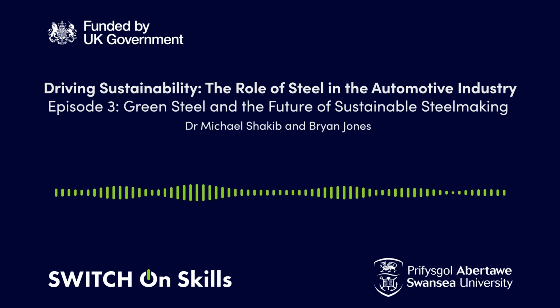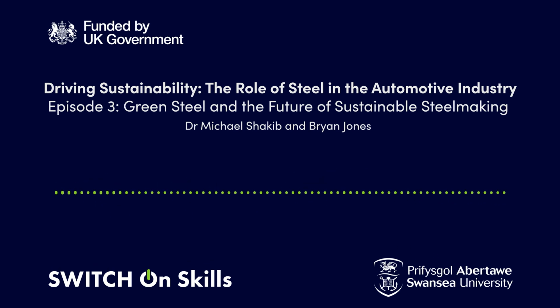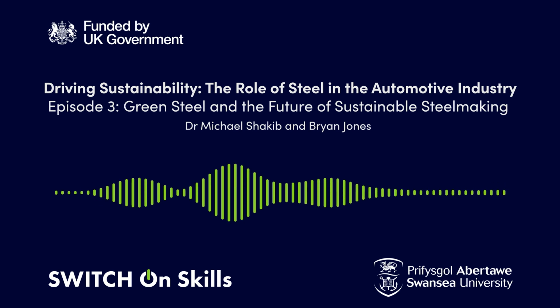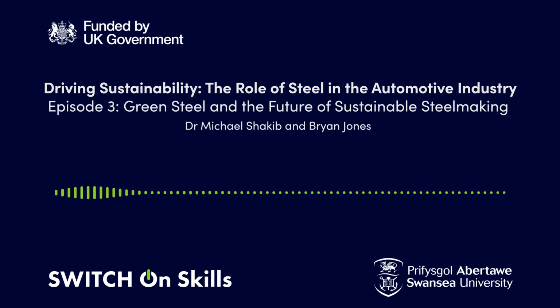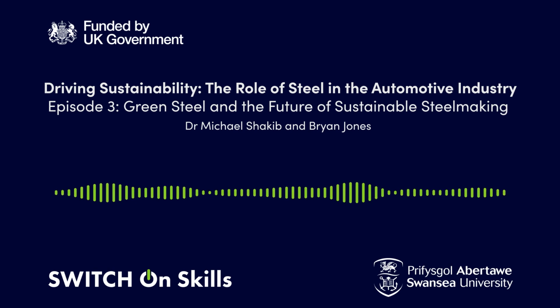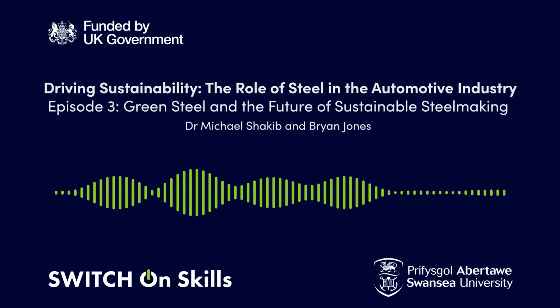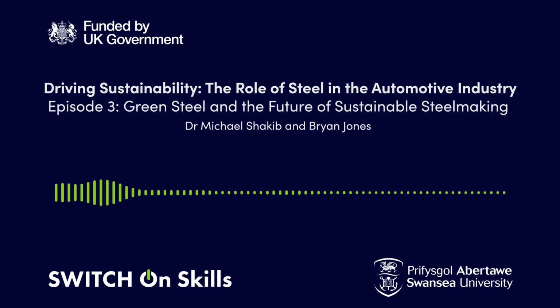But if you're looking at automotive, there are products such as interstitial free steels. We're looking at levels of carbon and nitrogen of 0.003 or 0.004. Incredibly low. So this imposes increasing stresses on the secondary steelmaking processes, such as vacuum degassing or vacuum tank degassing, to generate ultra-low carbon level products. And there are certainly challenges as well in making some of the very high-strength steels that are required in automotive applications, such as dual-phase steels, ultra-high-strength steels, hot-forming steels, and TRIP steels. So there are certain issues where considerable further development work is required in the use of electric arc furnace processes for satisfying all the requirements of the automotive market.